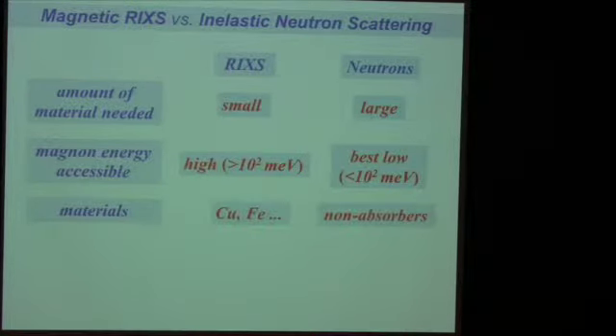Now let's look at materials. The good thing for neutron scattering is that you can do it on any system. You don't have to think about it, as long as your system does not absorb the neutrons and set off a nuclear reaction, you're fine. RIXS, as I said before, depends on each chemical element. It's a different edge. There can be different physics going on there. I'll skip the iridates now, but one reason to look at iridates with RIXS is exactly this problem. Iridium is a very strong neutron absorber, and therefore very bad for inelastic neutron scattering, while for RIXS, actually, it's perfect.